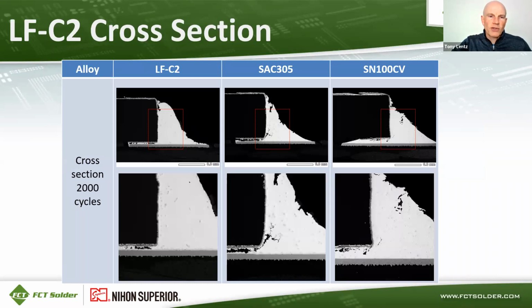Here are cross-sectional pictures of some of that testing. You can see the LFC2 cross-section shows very little cracking. There's a little bit of cracking going on underneath the body of that component, but otherwise up the sidewall, it looks pretty clean. SAC305 has much more cracking propagating from both underneath the component and from the top down through that solder joint. And then SN100CV is in between these other two, where there's some cracking propagating from both surfaces, but not as dramatic as the SAC305.